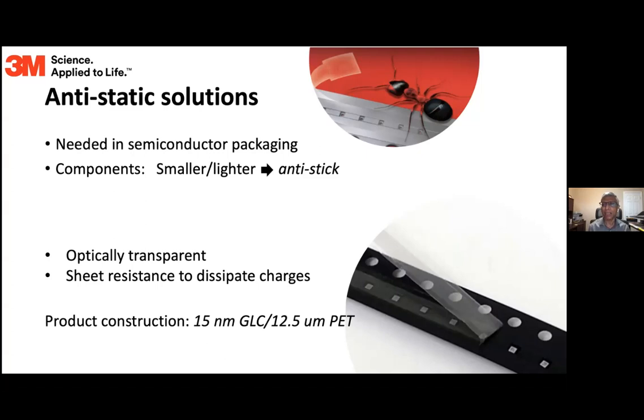So anti-static coatings become very important in this industry. Typically people use metallic coatings, which is not the greatest for the environment. What we did was put 15 nanometers of this graphene-like carbon material, and you can tune the static decay. For static decay, you need the right resistivity of the material, but the machine has to see optically through the packaging to identify the microchip. It has to read the barcode. So you compromise a little bit on both properties, and you can make a very nice anti-static coating using this. This is a commercialized product as well, using graphene-like material.